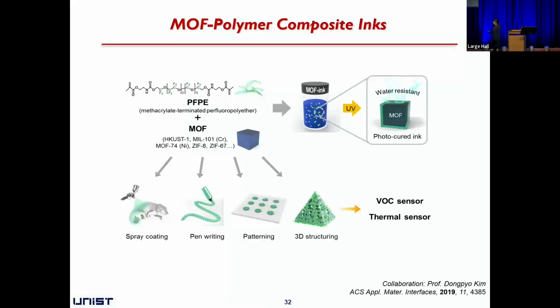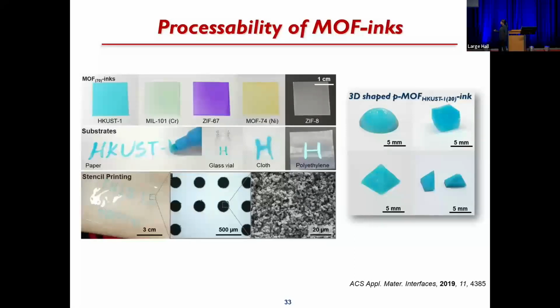Here the polymer is PFPE. This is a highly fluorinated hydrophobic polymer. And interestingly, this polymer is in liquid phase at room temperature. It means that it is very easy to make a MOF ink at room temperature. Just by mixing with the MOF powder, we can prepare the MOF ink. And more interestingly, this polymer is a photocurable polymer. So just by irradiating UV light, we can solidify it when we want. So we can coat, we can write, we can print, and we can shape with this polymer MOF ink.